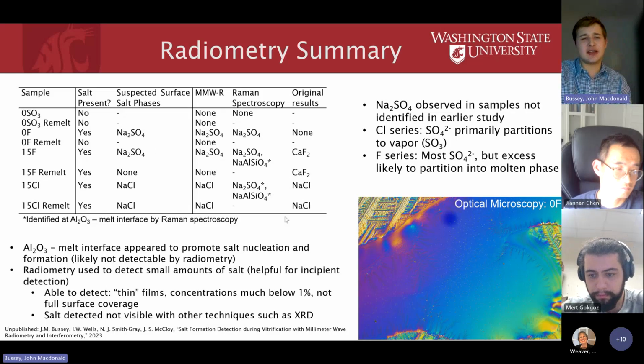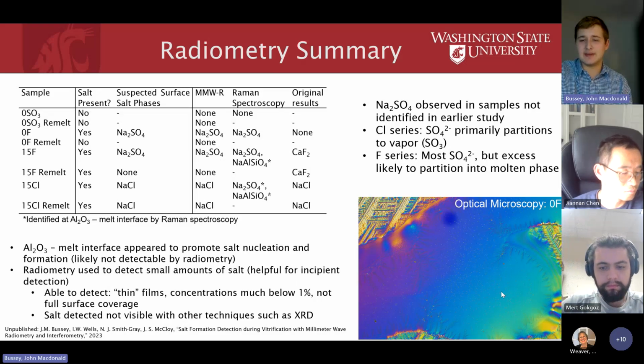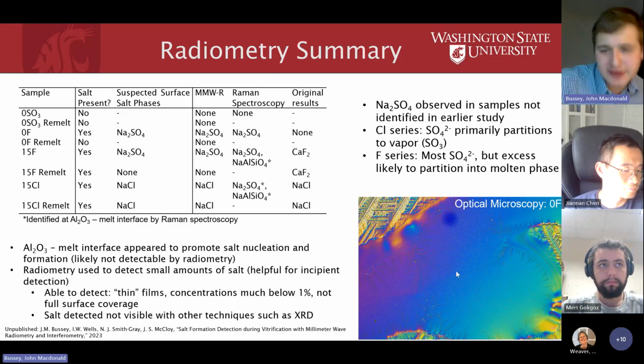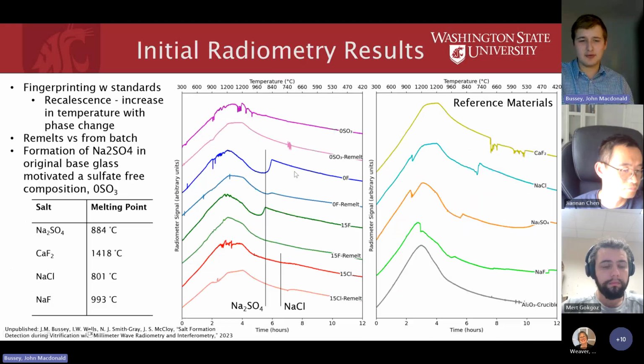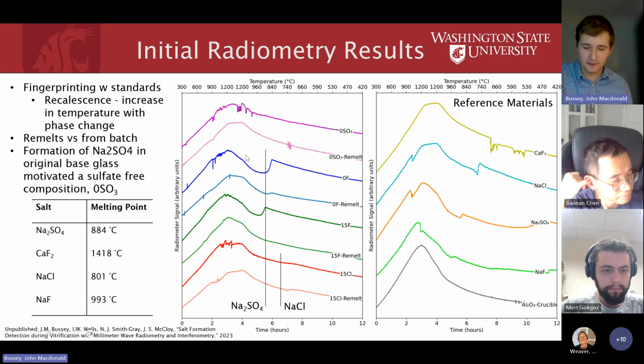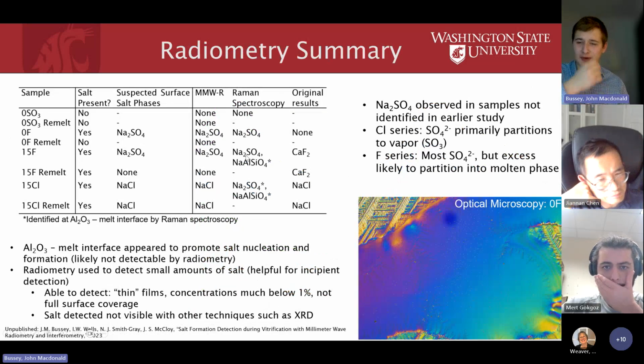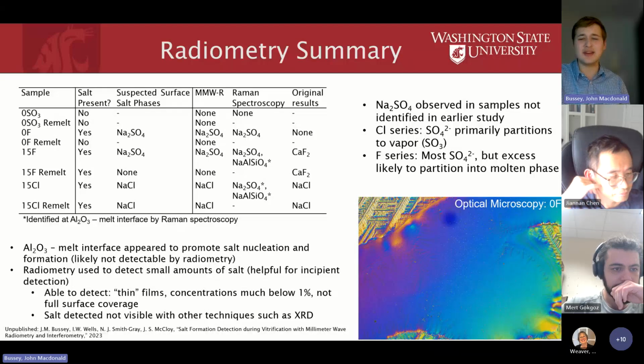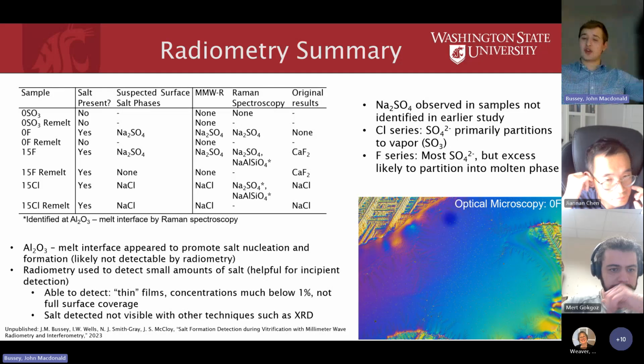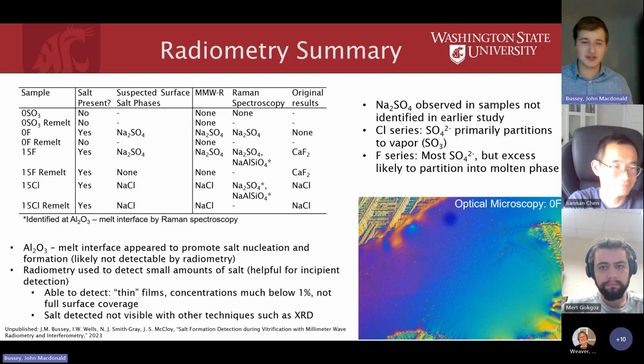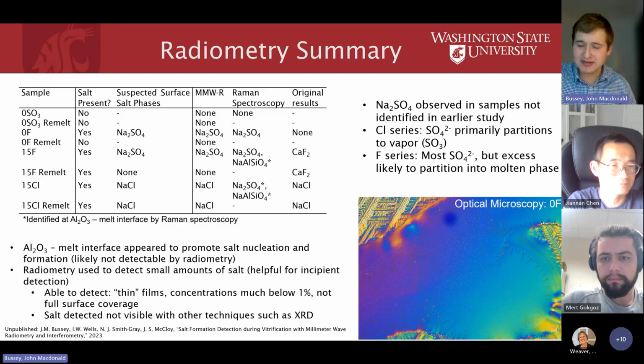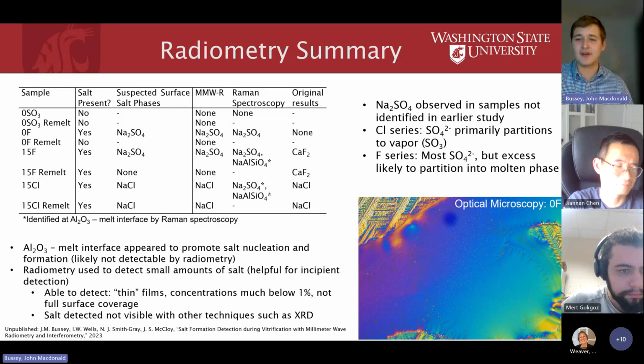Another thing to note is here in the bottom right corner, you see an optical microscopy image, and this is of the sample here in dark blue, where we see some of the most clear salt formation. We looked at the optical microscopy, and the salt only covered maybe 20%, 30% of the surface. And so instead of forming a large salt layer at these concentrations, they're forming small patches of salt. That's a good sign, because that means our system is able to detect incipient salt formation, when it's first forming, instead of only when it's formed a large significant layer, maybe like an electrical method would.